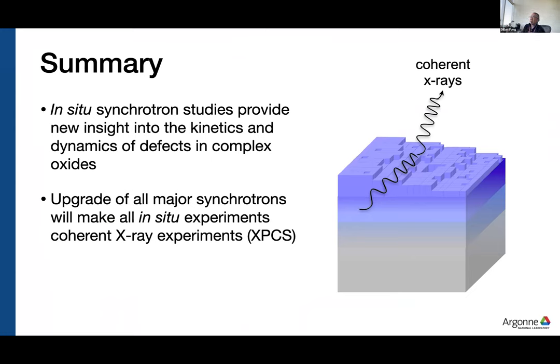So in summary, we've done a lot of in situ synchrotron studies into oxygen vacancy behavior in strontium cobalt oxide. We are trying to do most of the experiments with a coherent beamline, like at sector 8, so we can study the dynamics of oxygen vacancies moving in and out of our samples. I would encourage people listening to take advantage of these major upgrades to the synchrotrons. ESRF is done, and we're doing ours now. If you have a coherent light source in the area, I urge you to do some XPCS experiments. A lot of people want to do CDI experiments, but if you're interested in operando or in situ studies, like for switching experiments, you should look at XPCS. And that's it. I'll be happy to take questions.